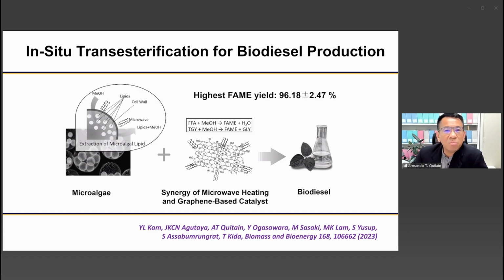So the results have been published. If you are interested, you may want to also browse the results in this journal. So this is promising because normally it undergoes drying. We can avoid the highly costly process of drying microalgae followed by extraction of the oil. But this is in situ. The methanol will react and at the same time extract the oil present in microalgae using microwave. And the good thing is with microwave, we can also disrupt the cell wall for more efficient extraction of the oil present in microalgae.